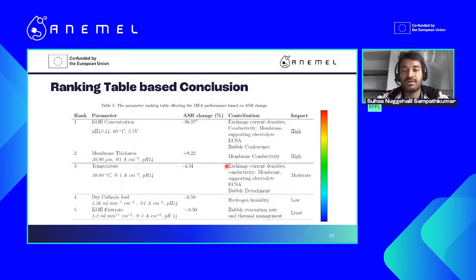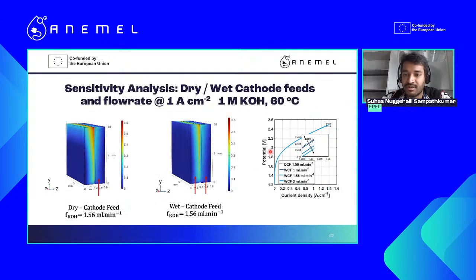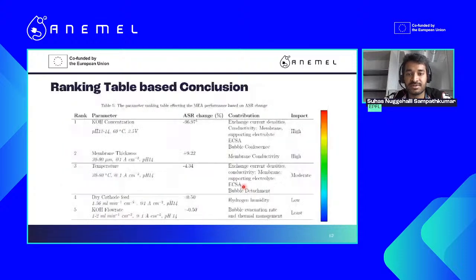So based on the ASR, which is called the area specific resistance, basically the slope of the IV curve here, what you see is the potential versus current density. If you fix a point, we fixed 1 ampere per centimeter square for the parameters where we could fix current density, and 2.5 volts for the parameters where we could fix the voltage, for instance.